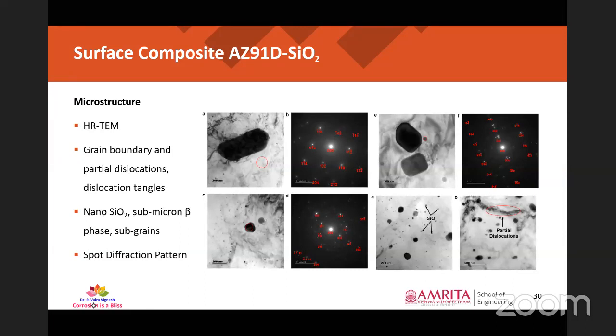And added to that, we have observed a spot diffraction pattern of the phases that are present in this composite. The spot diffraction pattern over here also confirms that the region which is bright is magnesium, and the very small region over there is going to be my nanophase silica. That was confirmed using this spot diffraction pattern. And submicron beta phase particles are also observed, and confirmed through this spot diffraction pattern too. And these partial dislocations could be observed from the figure at the bottom rightmost corner, and we could observe the dispersion fashion of the silica particles and submicron particles in the grains too.